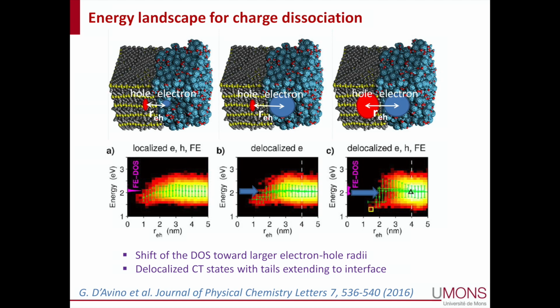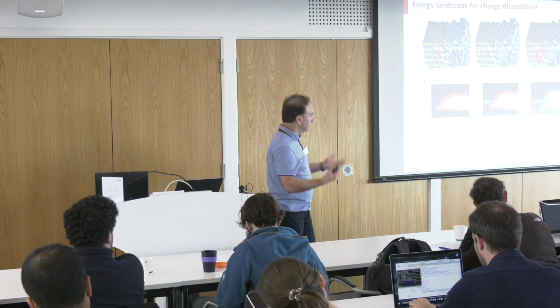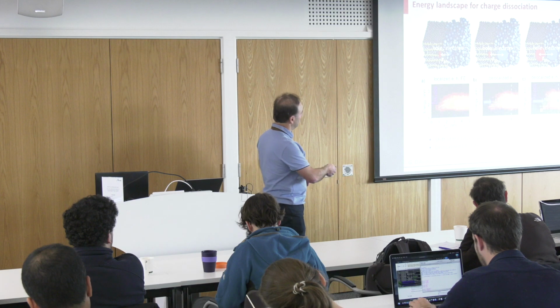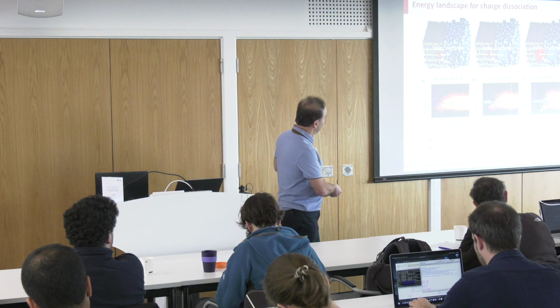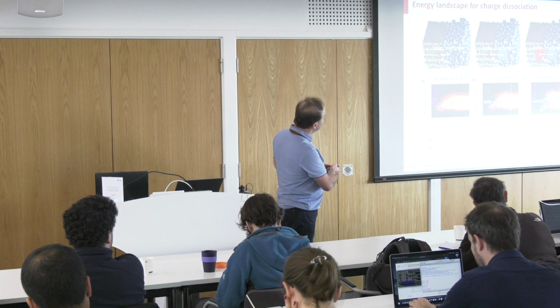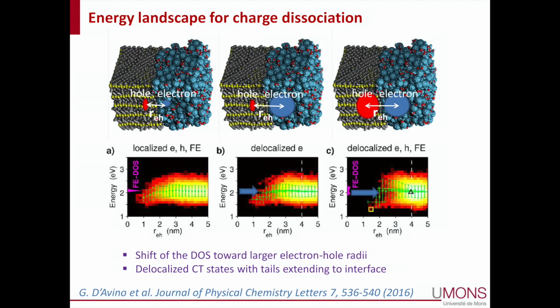So what we do in those simulations, we force an electron to be sitting here, a hole sitting there, and we do the calculation and we repeat this over many realizations of the disorder to end up with this distribution. If you now allow for the electron to delocalize, you now include the quantum mechanical interaction for both the holes and the electrons, then you see that the distribution is shifted towards larger distances. So essentially, you push the distribution towards these larger electron-hole separation values.